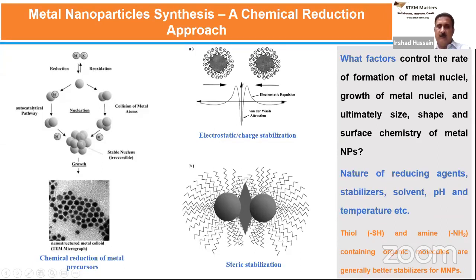But if you really want to use these particles for applications in nanoelectronics or nanooptics, in which you really need highly stabilized particles, then you need to covalently attach these long chain molecules to the nanoparticle through covalent linkage. And normally these long chain molecules have thiol or amine functional group at one end. So they will covalently link to this. And once they completely coat the surface of these nanoparticles, then due to their steric repulsion, these particles will not agglomerate. And you can basically freeze dry or simply dry these particles and keep them in the form of powder and use them later whenever you want. So they are really extremely stable.